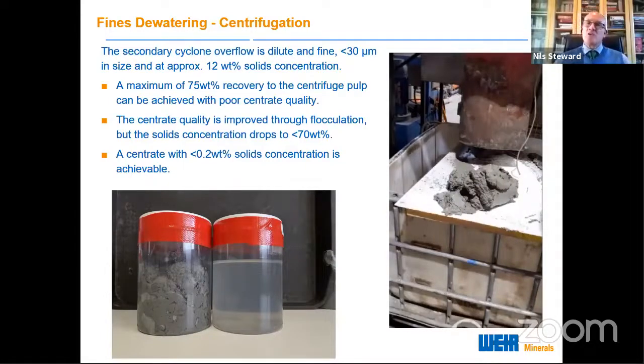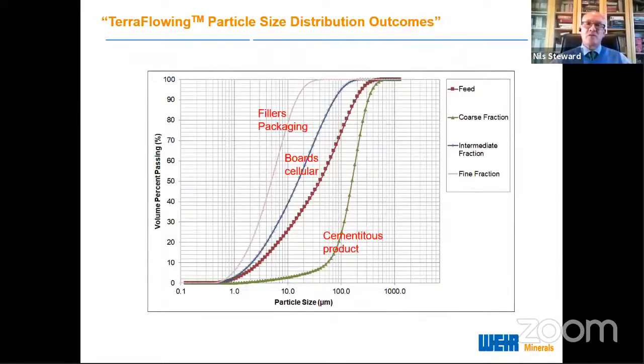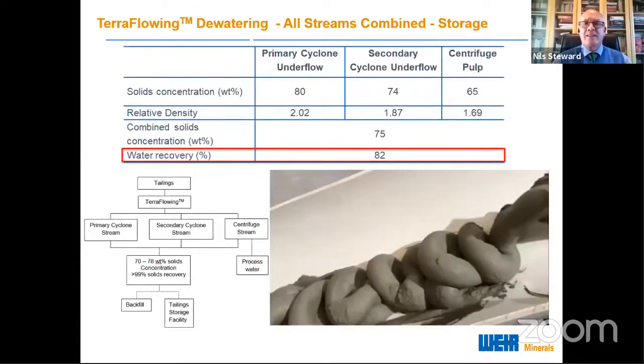So now we've actually got our 3 particle size distributions. We've got them in forms that we're able to deal with immediately, whether we're manufacturing cements, whether we're manufacturing fillers, whether we're going to foam them. If we continue just looking at this as a mine storage opportunity, what we can do is take all 3 of those underflow streams, the primary cyclone, the secondary cyclone, and the centrifuge pulp, and we can combine those.